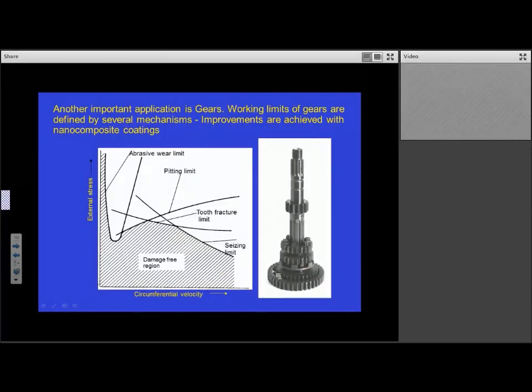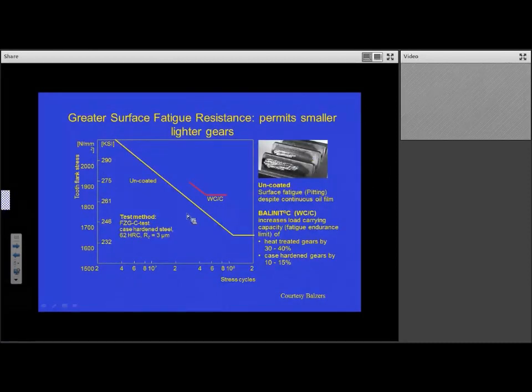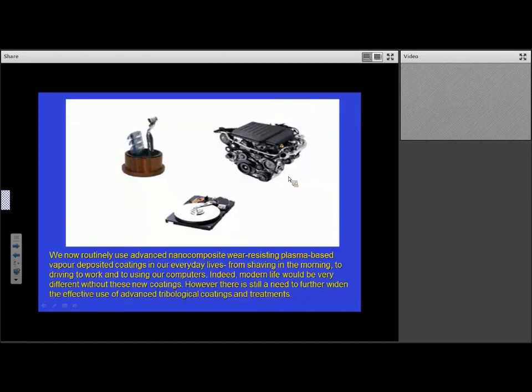Those coatings are used in all kinds of things. Gears, as an example, where you wouldn't think they would work, but they expand the damage-free region for all these kinds of wear mechanisms and failure mechanisms. And this shows a typical gear and the effect that the coating, nanocomposite coating or nano-lead coating, can have on the fatigue life, on the fatigue limit, the stress that can be applied without any fatigue occurring. So these very thin coatings, maybe only 3 microns thick, can protect these gears under very arduous contact fatigue situations.